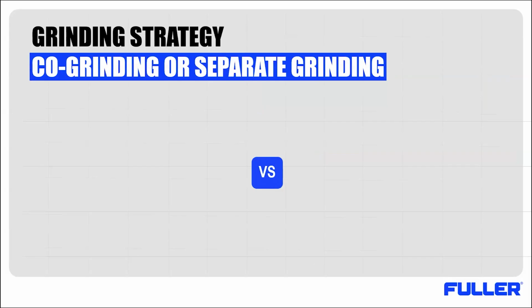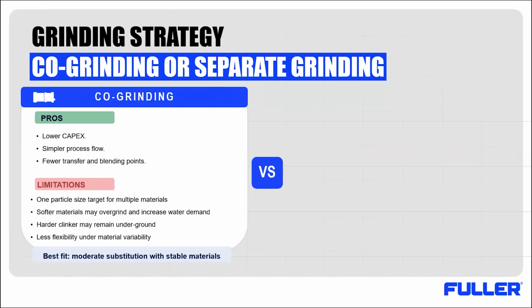Once we understand the PSD principle, the next question is how to grind the material. Co-grinding is the simpler route. It usually means lower capex, fewer equipment, and simple process flow. For moderate substitution with a stable material, it can be a practical solution. But the limitation is that all the material is forced into one grinding target. Softer SCMs may be overground. At the same time, harder clinker may remain underground.